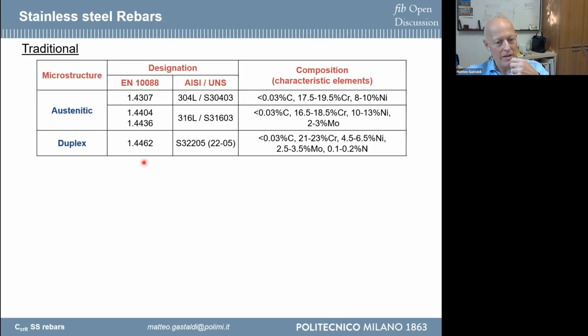Another kind of stainless steel that is used is duplex stainless steel, generally 2205, which contains a high amount of chromium, 22%, higher than the austenitic one, a lower amount of nickel, around 5%, and a high amount of molybdenum and also nitrogen. This affects the corrosion behavior. This is the traditional one.